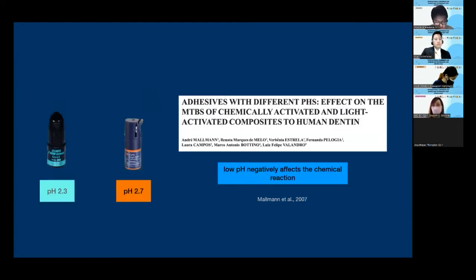The result of combining its universal adhesive and Panavia SA Luting Multi failed to show higher bond strength. It could be that the lower pH of Clearfil Tri-S Bond Quick, compared to Single Bond Universal, negatively affects the chemical polymerization of the resin cement. Mallmann and colleagues state that the low pH of the adhesive system negatively affects the bond strength on dentin when using chemically activated resin cement.